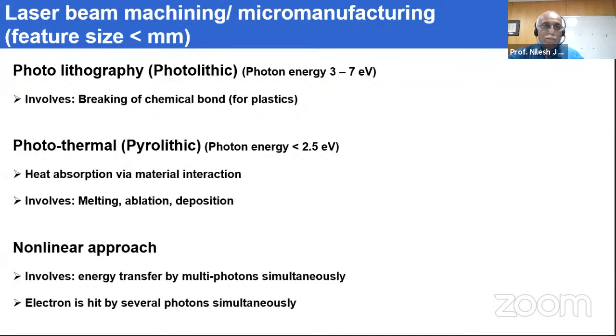Laser beam micro machining involves light-matter interaction with a feature size less than the millimeter order. Lasers have specific characteristics such as coherence, narrow spectral width, and well-defined spatial and temporal characteristics, which are very useful for producing micro features on metals, semiconductors, polymers, composite materials, and ceramics. Laser processing is a non-contact process that provides very high resolution and precision due to localized heating and minimal redeposition. It allows not only material removal — drilling, cutting — but also welding, additive manufacturing, and surface structuring.